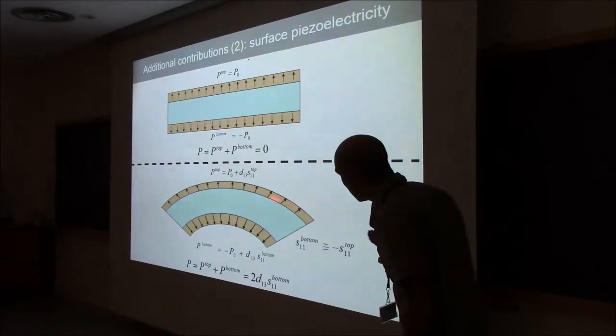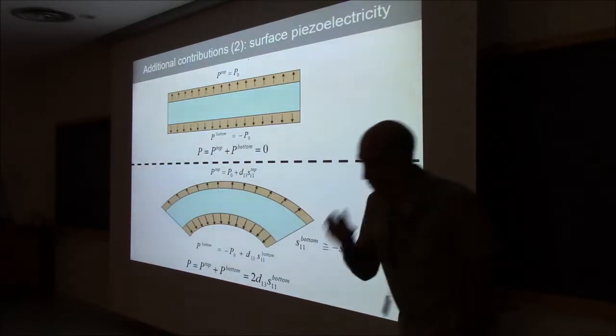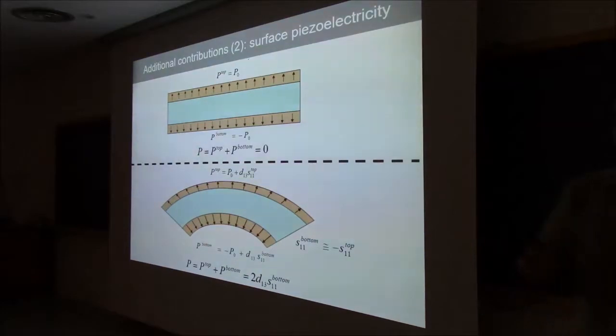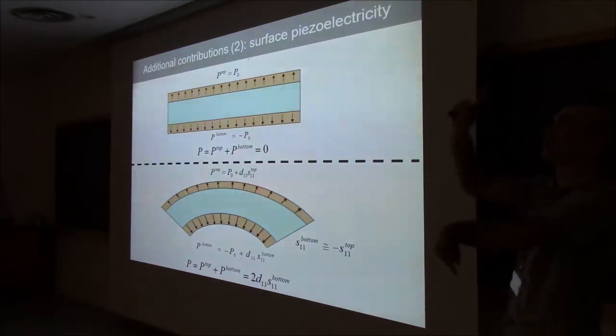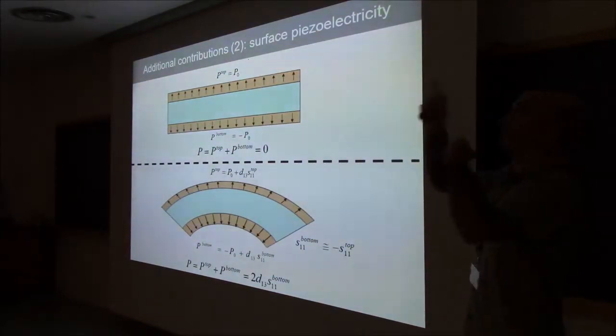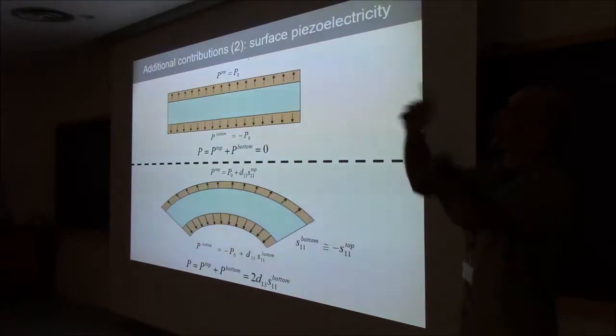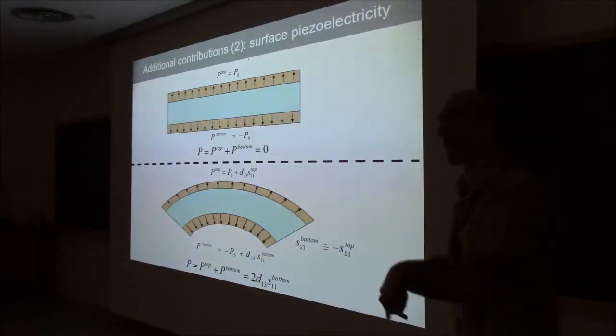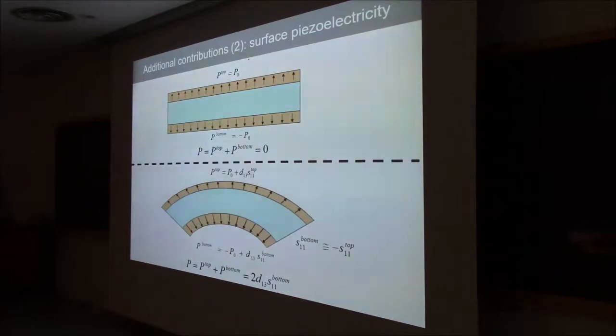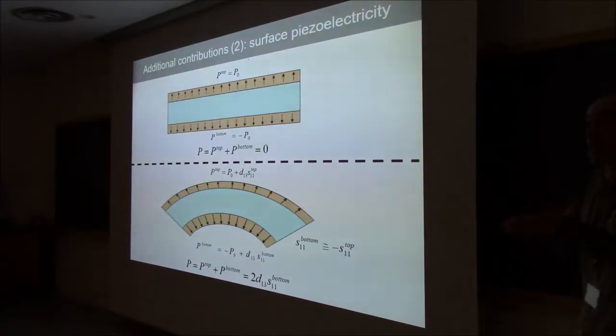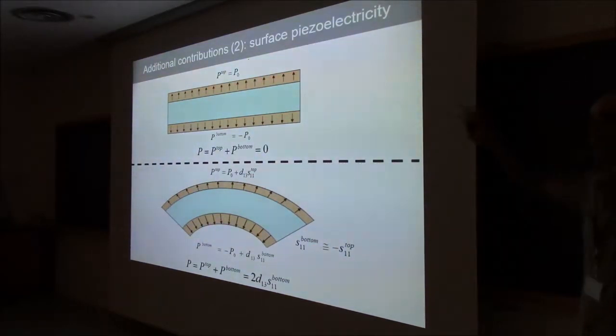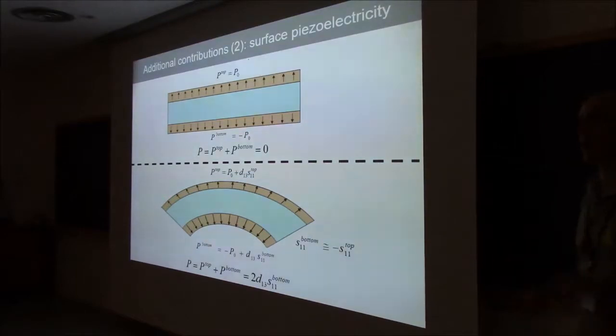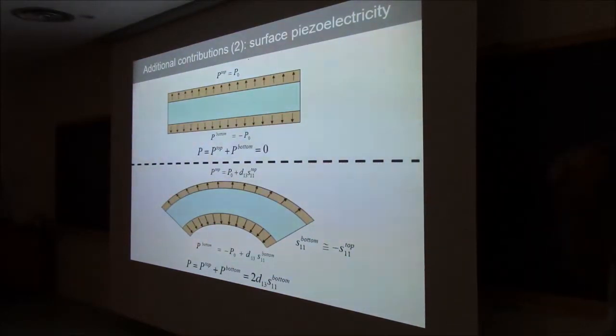now here I am extending, here I am compressing, which means that the strains that I am applying are of opposite signs. So now the two contributions that were previously opposite to each other, if you apply a strain of the opposite sign to something that is opposite, what you get is two polarizations that point in the same direction. Therefore, when you bend your crystal, you will get a net surface piezoelectricity that comes just from the surface. And that's ignoring the fact that your material is flexoelectric. Just from the surface. You bend any crystal, and the surface will give you a surface piezoelectric contribution.